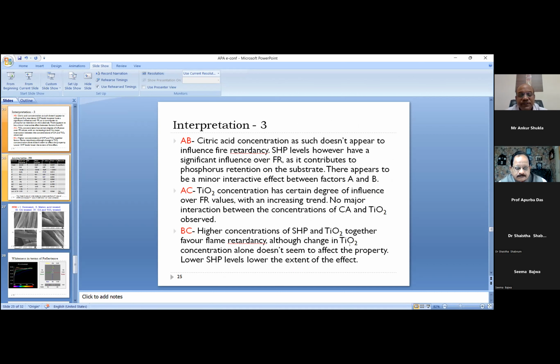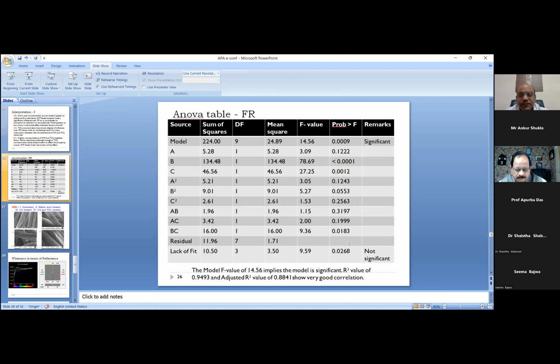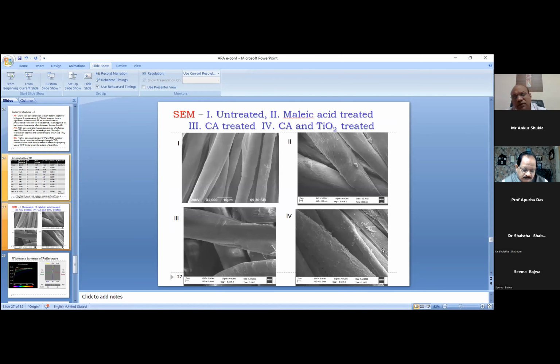So higher concentration of SHP and TiO2 together favor flame retardancy. And as such, the change in TiO2 is not significantly contributing to it. And lower SHP or sodium hypophosphite levels lower the extent of the effect. So this is the table. So here the model is significant, which is automatically calculated by the software, and again, lack of fit is not significant here. So that is what we wanted. So we are getting all the three properties to a reasonable extent when they are suitably combined. I mean, when the chemicals are suitably combined.